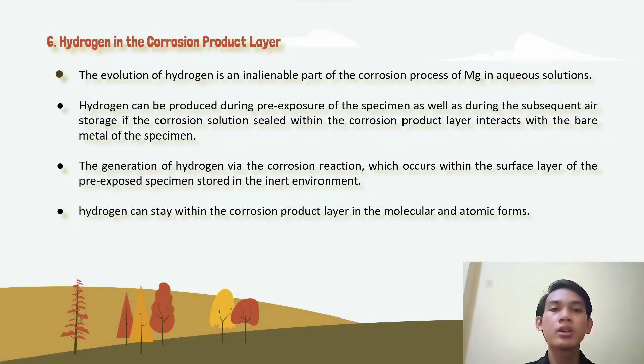6. Hydrogen in the corrosion product layer. The evolution of hydrogen is an inalienable part of the corrosion process of Mg in aqueous solutions. Hydrogen can be produced during the pre-exposure of the specimen as well as during the subsequent air storage, if the corrosion solution sealed within the corrosion product layer interacts with the bare metal of the specimens. The generation of hydrogen via the corrosion reaction occurs within the surface layer of the pre-exposed specimen stored in the inert environment. Hydrogen can stay in the corrosion product layer in molecular and atomic forms.